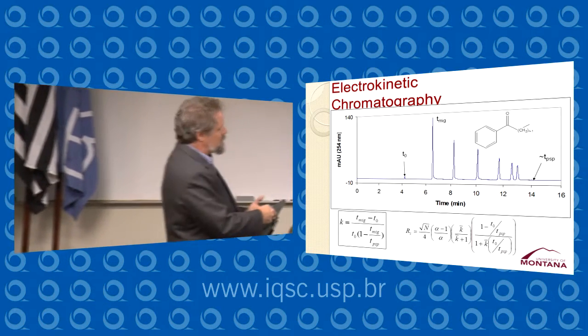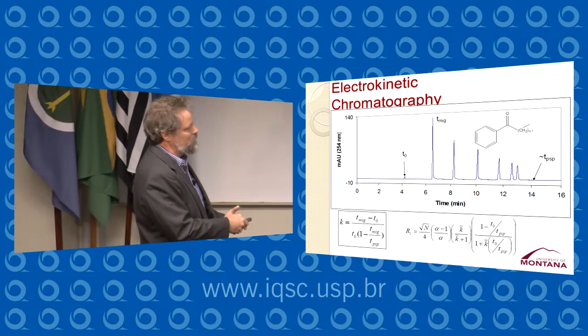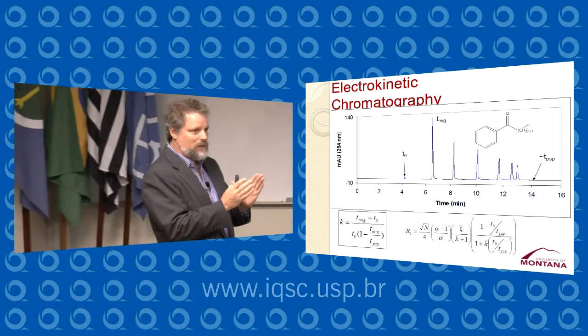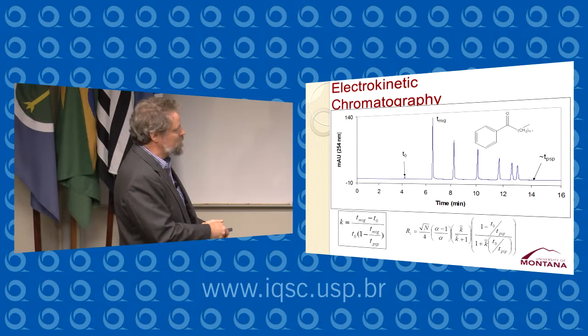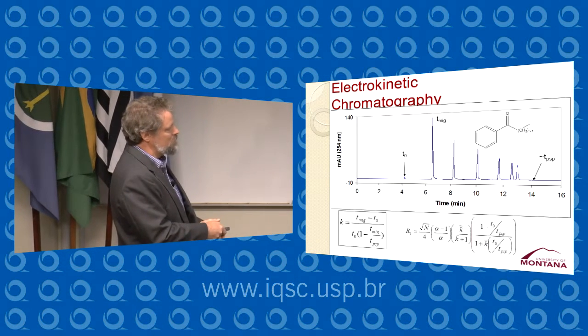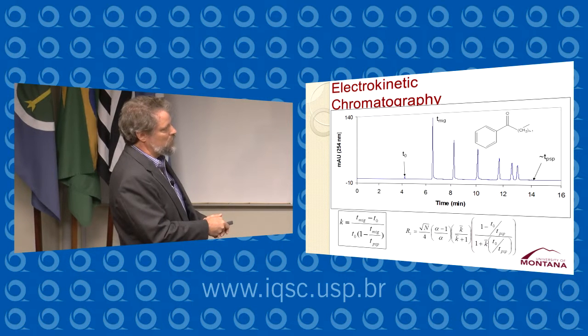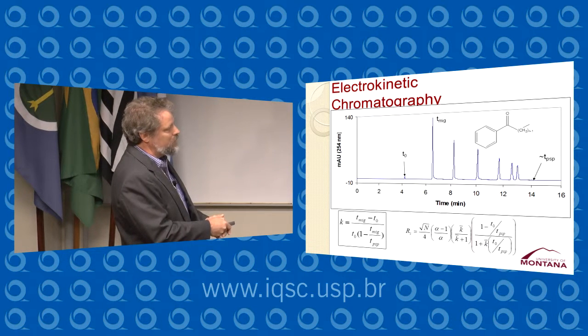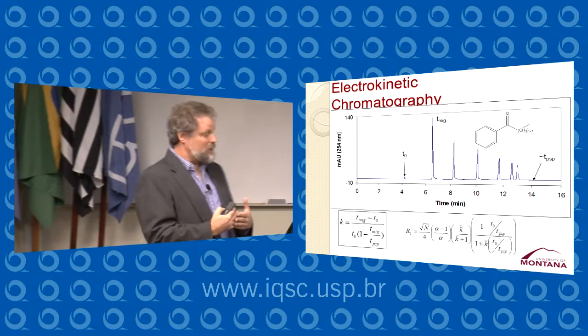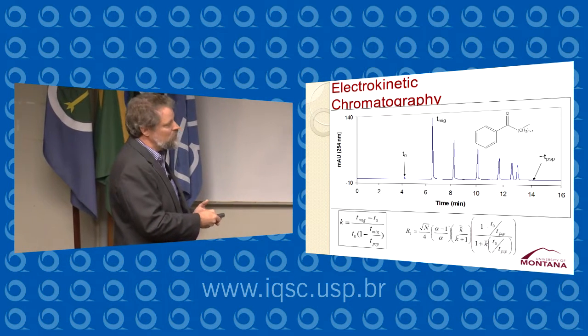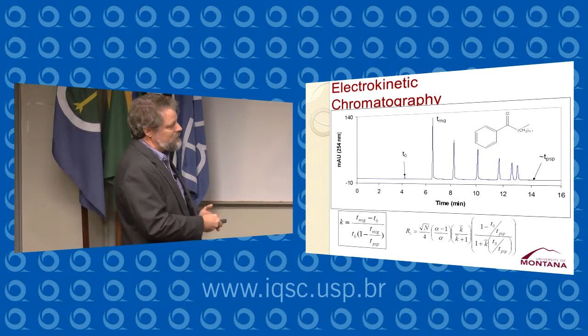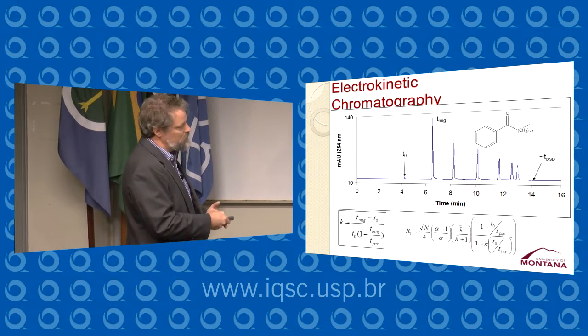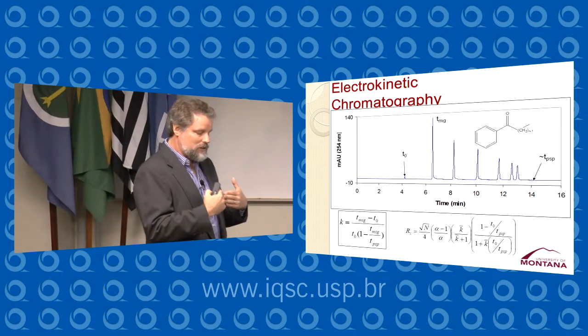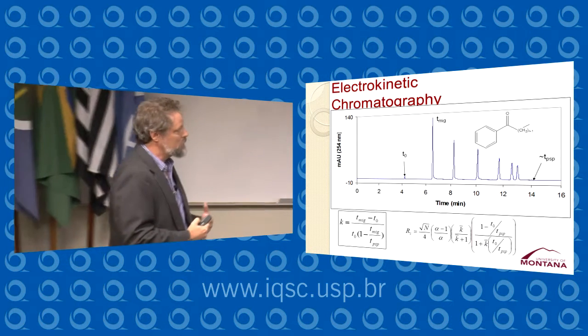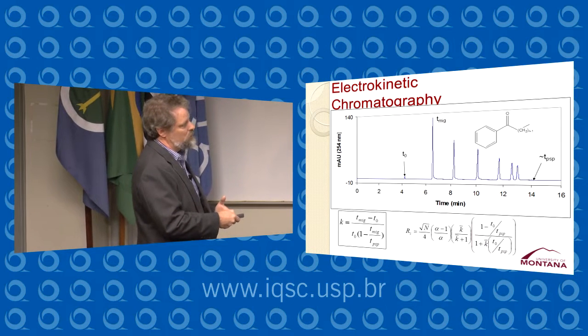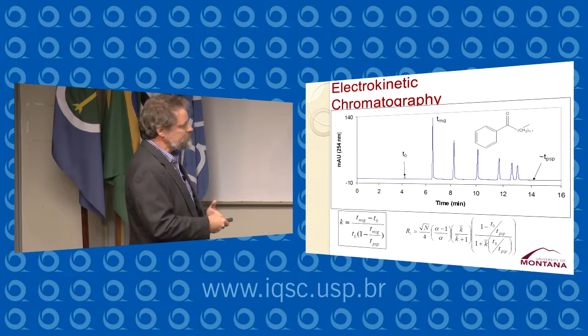What we know about this homologous series is that each compound in the series, the selectivity between each compound in the series, the selectivity is the ratio of the retention factors. The selectivity is the same for each of these pairs. But as we get to later and later elution times, migration times, we see that the resolution is getting worse. And that is shown in this equation, that as our migration times become closer and closer to the retention time or the migration time of the pseudostationary phase, we'll start to lose resolution.